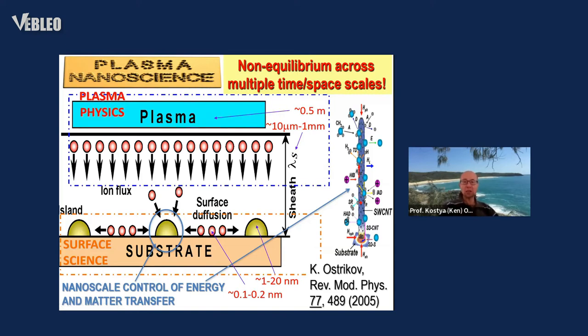When such interactions take place, they essentially herald the nanoscale control of energy and matter, the exchange of energy and matter between the plasma phase and the growing particle, which happens over very small scales, such as the size of this particle, which, as I said, is of the order of nanometers. One great example is the carbon nanotube, where you can see on the surface of such a small object, myriads of various reactions may take place. And not only on the surface of the nanotube, but also on the surface of the small catalyst particle from which the carbon nanotube actually grows.